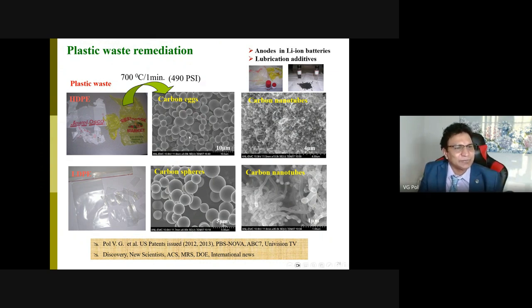So back in 2010-12, we were also making carbonaceous material, dissociating this plastic bag in a closed container, making sure that we do not expose anything to the environment. And eventually we could make carbonaceous material, very nice black particles, spherical in shape, and carbon nanotubes.